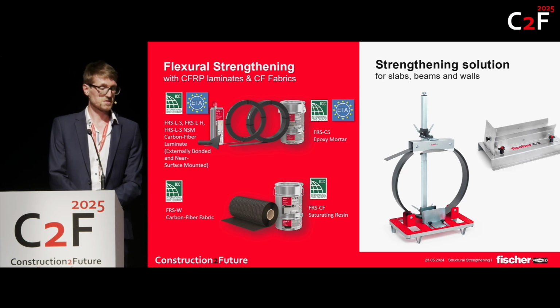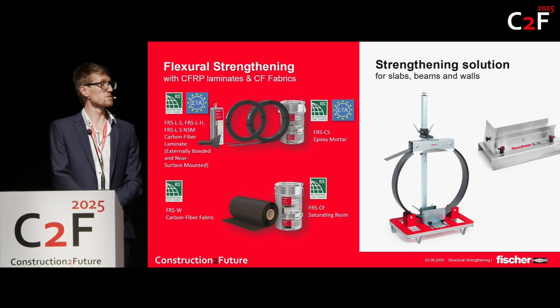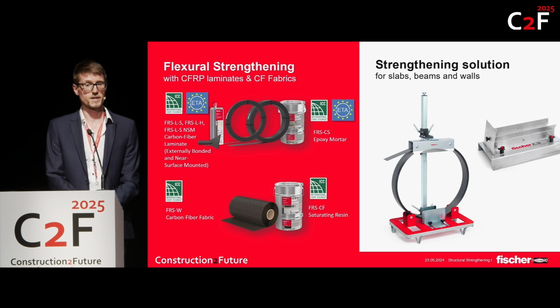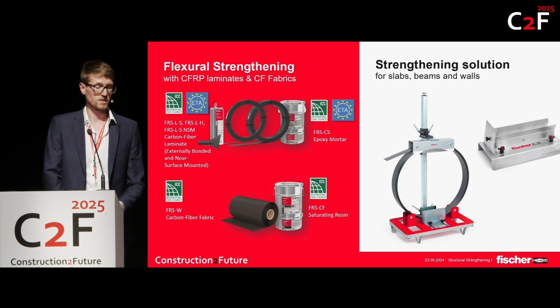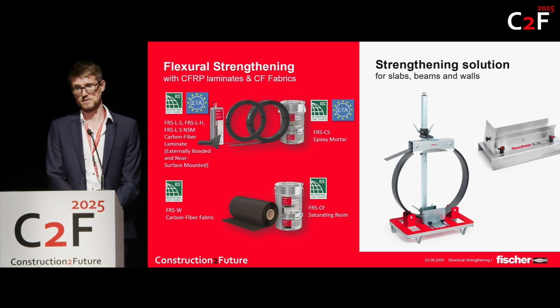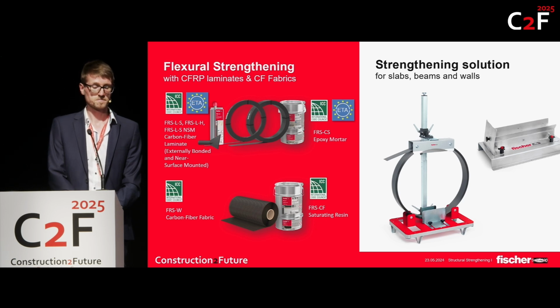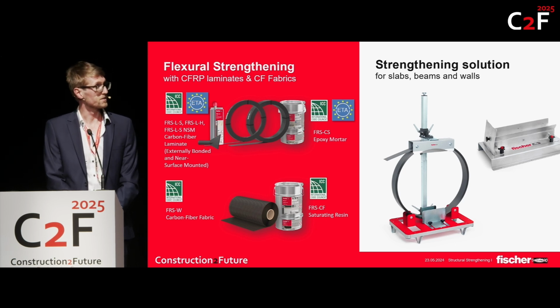And since, as I said, we put emphasis on customer benefits, we also developed a series of application aids, such as a laminate uncoiler to uncoil the large 150 or 100 meter CFRP coils to cut them to length rather easily. And mortar application tools in order to ensure that you have the same amount of resin and the same profile of resin on the CFRP laminates at all times, to keep the construction site tidy and, again, to be quick.